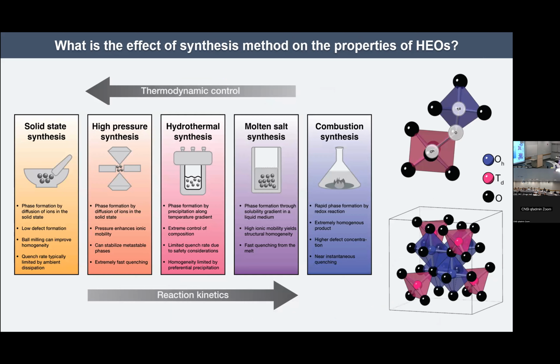So what we set out to do is to grow a single high entropy material with nominally identical composition, nominally the exact same chemical formula, by five different synthetic methods, all in bulk, that would sample different thermodynamic and kinetic reaction conditions. They're sorted on this rough axis. It's not completely perfect, but generally going from left to right, we're improving reaction kinetics, and going right to left, we're accessing more thermodynamic control, so we're more likely to be accessing the thermodynamic ground state. These methods occur in different media. Solid state is a solid-to-solid reaction, whereas in combustion, we're dissolving all of our reagents into a solution and making a gel. So these are very different processes.